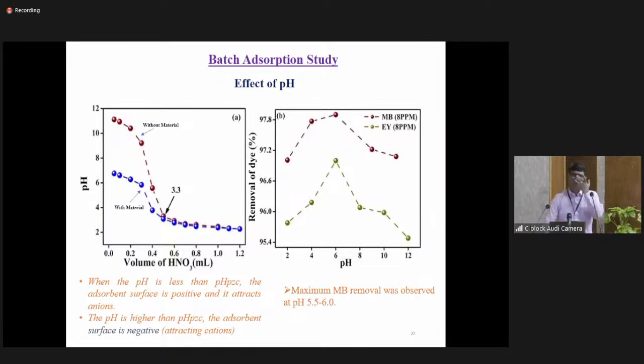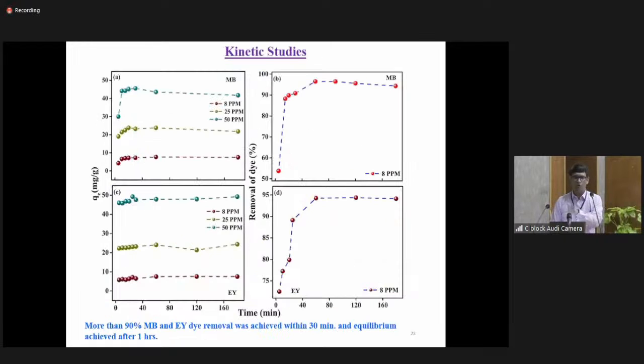Then similarly, you can see its effect with the pHpzc, which was also taken in a similar way. And then we found, not going into too much of the kinetic details, it's taking around 30 minutes only to remove 90% of the dye. So 90% of the dye was removed in only 30 minutes. Earlier, it was taking about 5 hours. So by using the carbon nanotube, it's helpful to remove the dye in an efficient way.